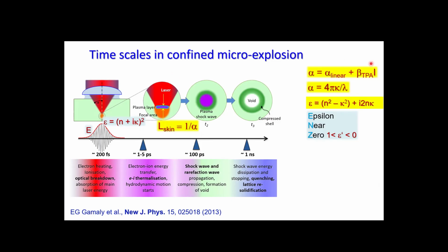But as we increase intensity, and this is happening at the very peak of our femtosecond pulse, we begin to have nonlinear contributions. What we are showing here for absorption coefficient is only 2-photon absorption, the first contribution. Once absorption is increased, we can localize the energy deposition into skin depth, which is proportional to 1 divided by absorption coefficient. So from energy deposition into the whole focal volume, we can do much better in terms of axial extent of energy deposition. We go to skin depth, and for highly ionized material, it is like in a metal, you can have tens of nanometers thickness where energy is deposited.